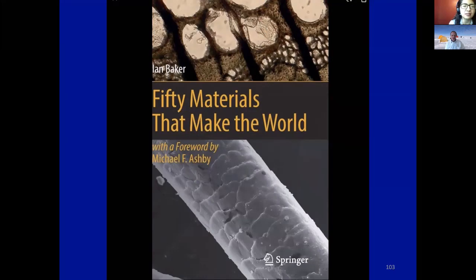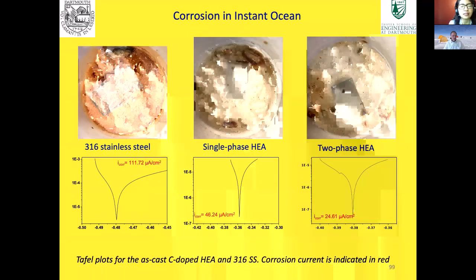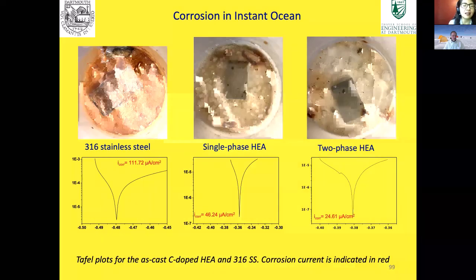And I also would like to ask you something related to corrosion resistance. How do you explain that the corrosion resistance improves in high entropy alloys, because these alloys have more precipitates? The precipitates are mentioned by diverse authors in the literature as stress concentrators, and stress concentrators are usually points with more reactivity. So usually corrosion and some chemical processes start at those points. So how do you describe the mechanisms that improve the corrosion resistance in this kind of alloy?